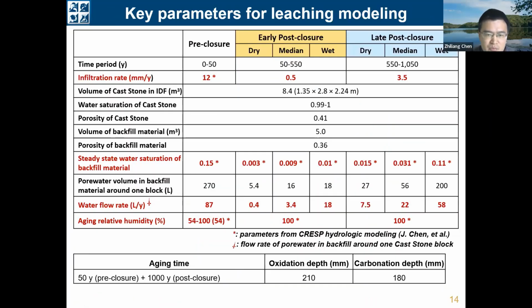And based on the output of the hydrological model, we have some key parameters as the input for the leaching model. So as you can see in this table, the big difference between the pre-closure and the post-closure is the infiltration rate and the corresponding steady state water saturation of the backfill material, and also the water flow rate around the Cast Stone. So the post-closure period is further divided into an early post-closure period and a late post-closure period. And for each period, 3 different cases, including the dry case, medium case, and wet case, are included.